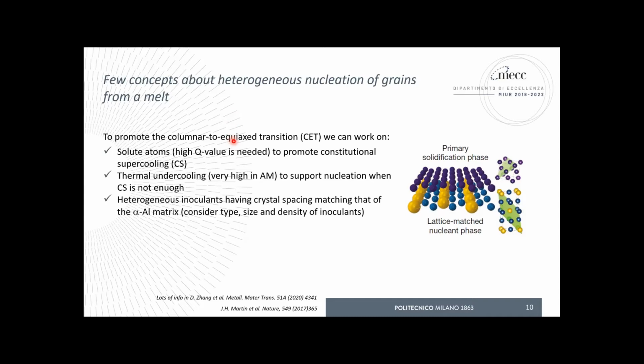First of all, in order to promote the columnar to equiax transition, we need to work on at least three main points. We need to have a number of solute atoms in the alloy that during solidification promote enough constitutional supercooling. In literature, we talk about the Q value, which needs to be high enough. Q stands for the growth restriction factor. So it depends on the partition between solid and liquid of a specific element, and we need to have enough segregation in the first layer of the liquid of the solute atoms. So we need to respect this condition. Moreover,